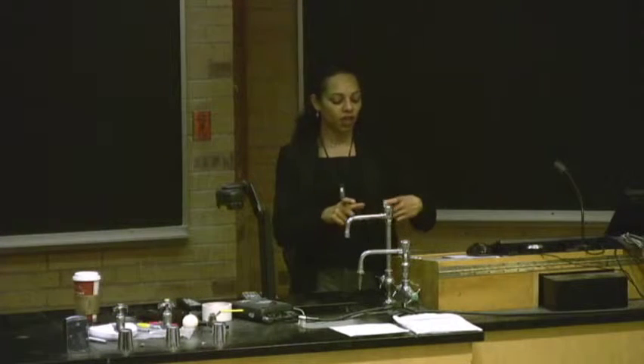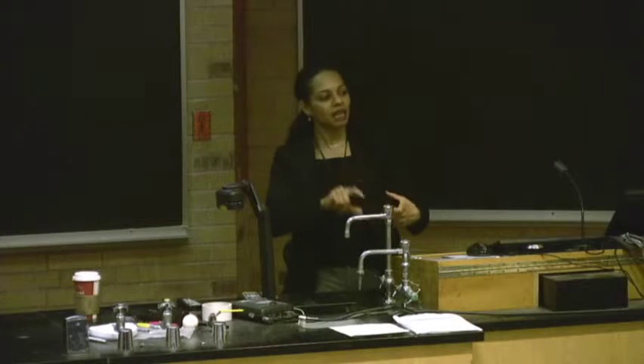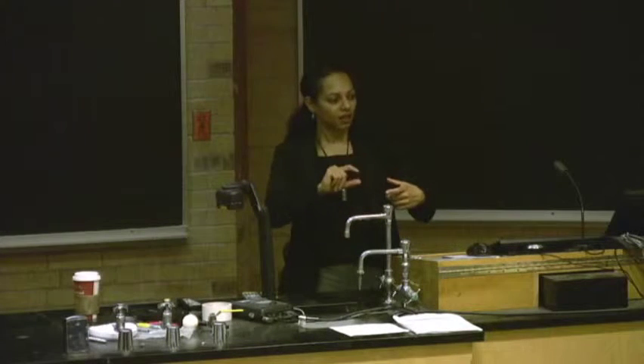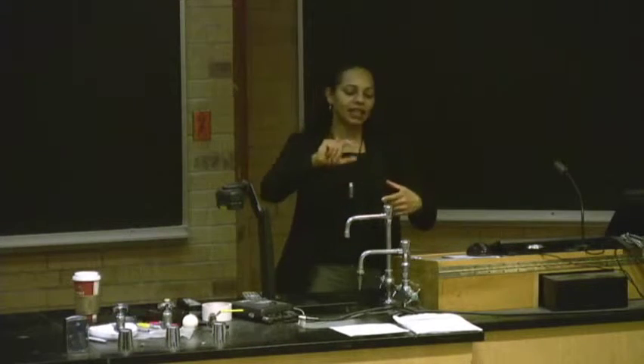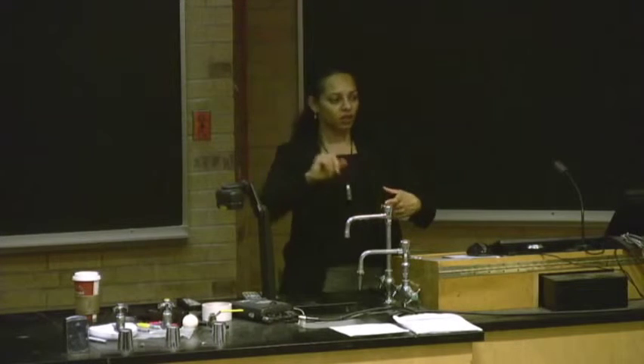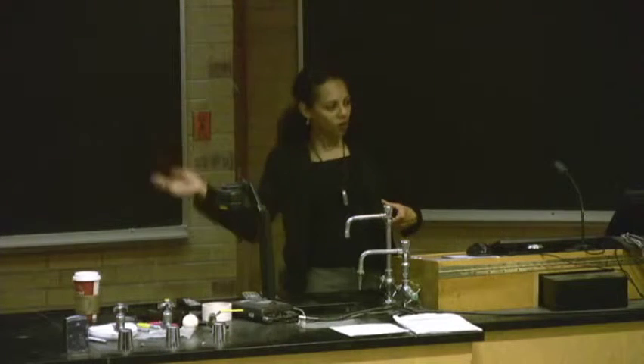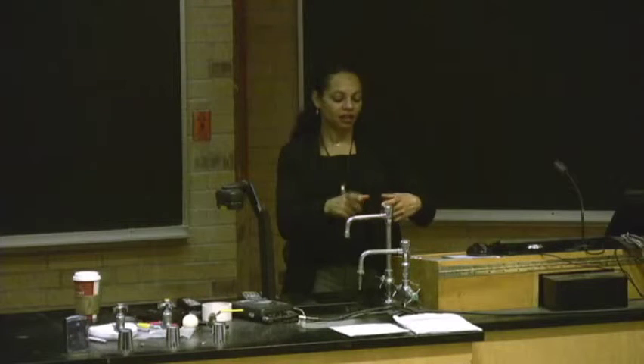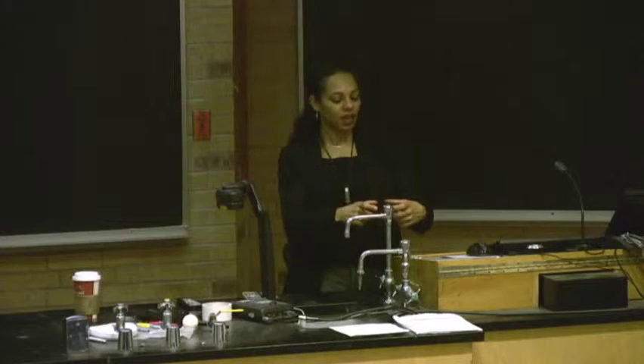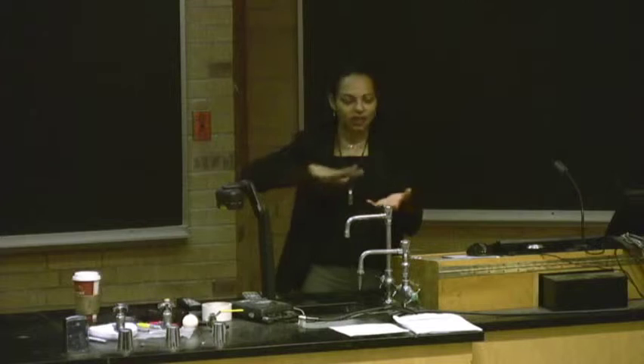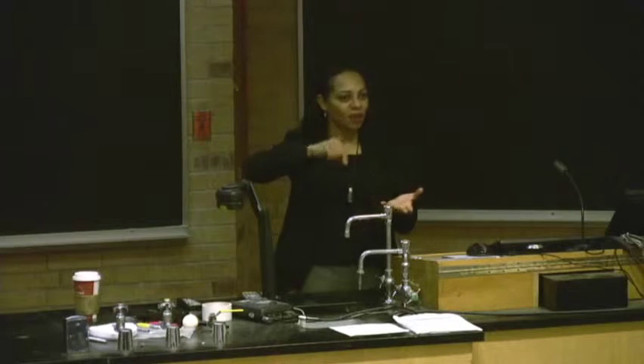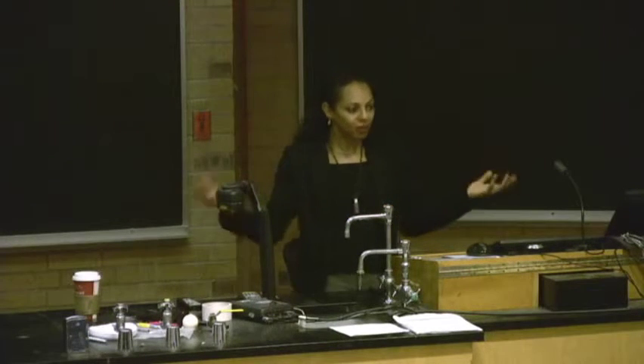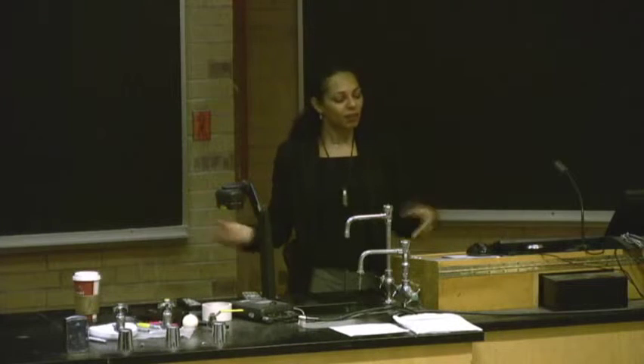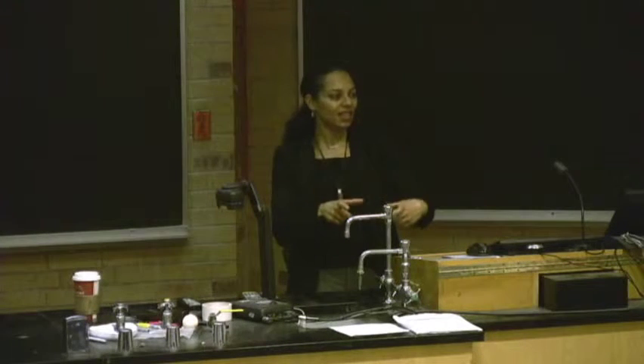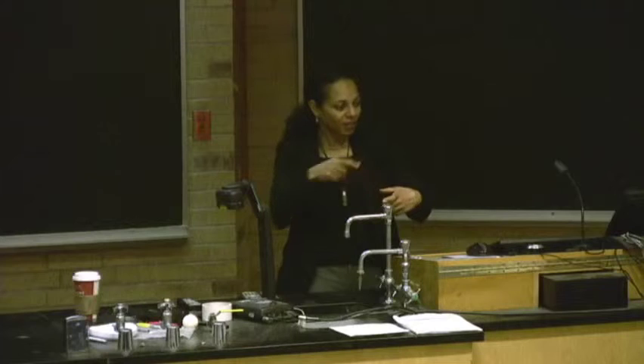It turns out that when you look at it under a microscope and you have a 300 nanometer silicon oxide layer under the graphene, you can actually see a difference between 1 and 2 layers and more. It's just some interference effect. If you don't have that oxide layer, you just see lots and lots of pieces of stuff, and you'd have to do an AFM on all of them to see the thickness, and it's impossible. It's too time consuming. But if you can optically see the graphene candidates, then you can find it and manipulate it. And that was the big difference there, which is sort of funny.